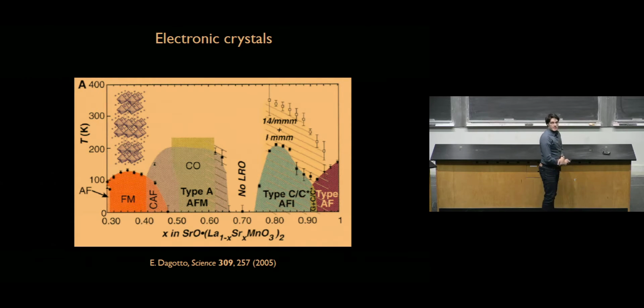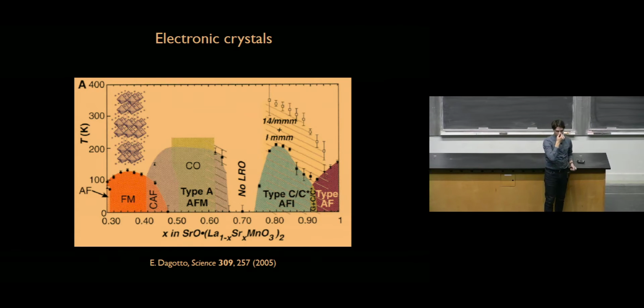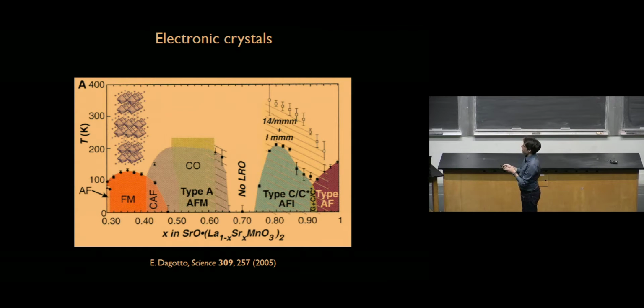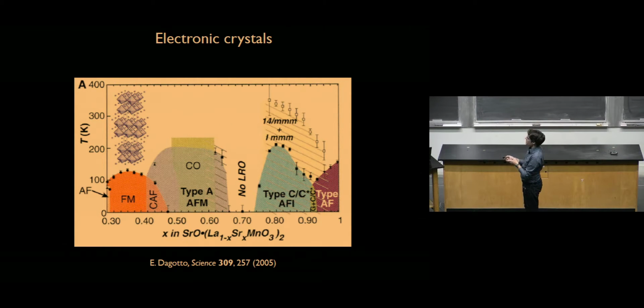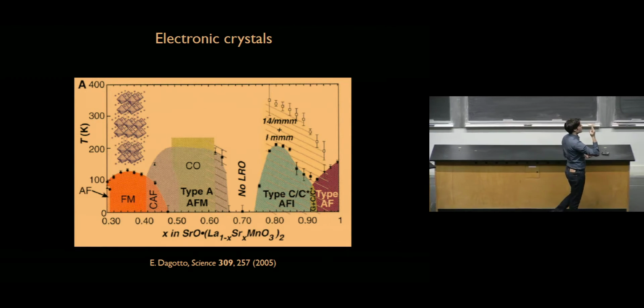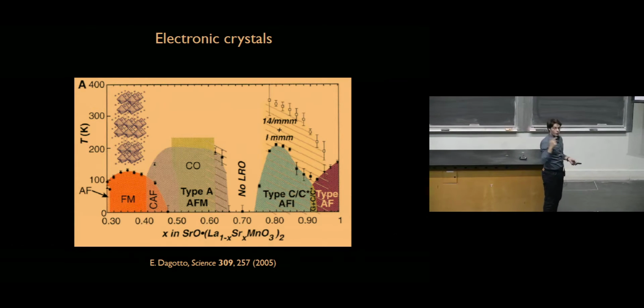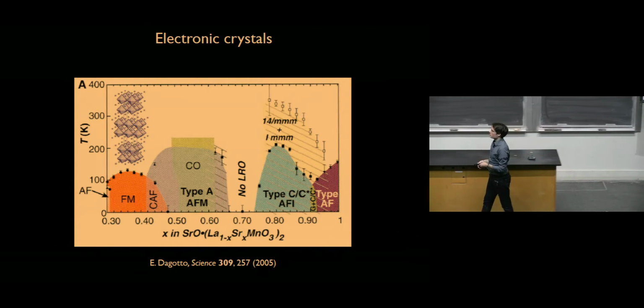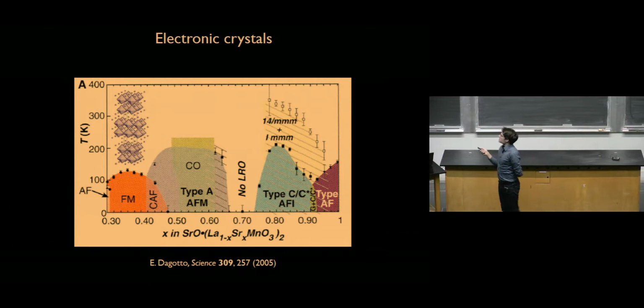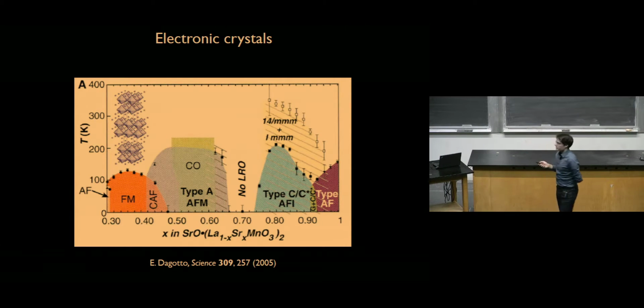This axis is temperature, as I anticipated. This axis is doping. Doping means you've added carriers in your material, and you typically do it with stoichiometry. So you have a certain stoichiometry here, and then you start adding some chemical species. In this case, you start adding strontium here. X stands for the stoichiometry of strontium. When you replace lanthanum with strontium, you have 2 atoms that have different oxidation states, so one of them will donate electrons or holes. That's how you dope your material with carriers. And this is the zoo of different electronic phases you can have in this kind of material.